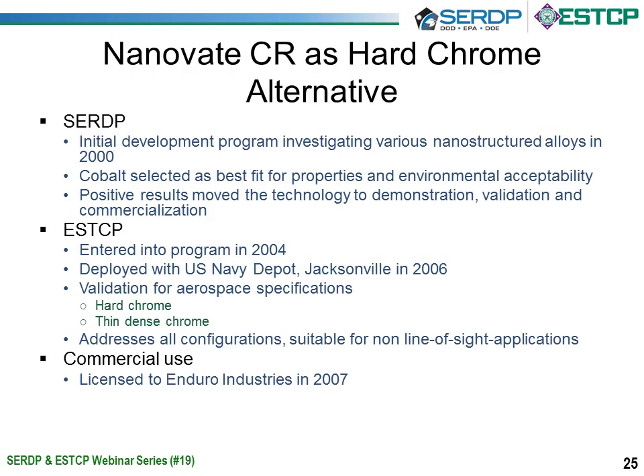So at the time, after the initial development, cobalt was selected as the best fit because it had the best set of properties and environmental acceptability. The positive results of that project then moved the technology basically to the demonstration and validation phase and ultimately to commercialization. So the ESTCP project entered in 2004, and that was the work involved with Jacksonville. And then the process was deployed to Jacksonville in 2006, where it was looked at for validation for various aerospace applications, which included both hard chrome as well as thin dense chrome applications. And it addressed all configurations, so it was suitable for line-of-sight applications as well as non-line-of-sight applications, such as coating the ID of cylinder bores.